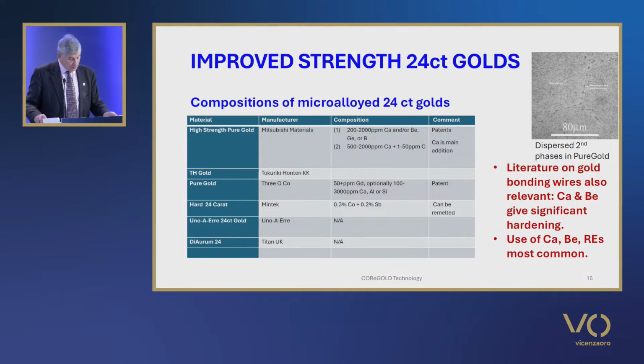The age-hardenable alloy is of 995 fineness and contains 0.3% cobalt and 0.2% antimony. It is based on precipitation hardening by a gold antimony intermetallic, AuSb2, with the cobalt retarding recrystallization. The gold antimony phase diagram is a eutectic system at the gold rich end and shows similar features to those I showed earlier.